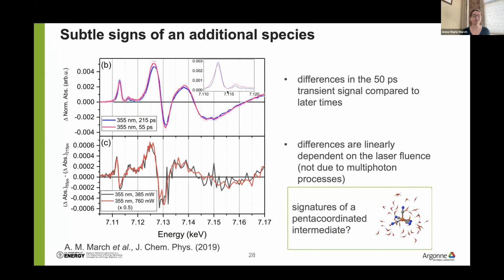Now, we were very careful to make sure that this was not some sort of nonlinear contribution, because this molecule likes to absorb multiphotons. So it's not. And so then we thought perhaps what we're seeing is a signature of a pentacoordinated intermediate.